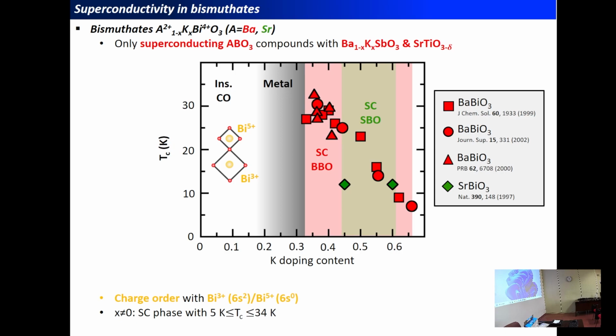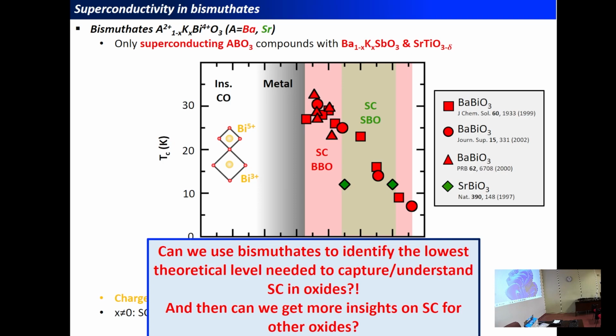But when you dope the material, either if it's barium bismutate or strontium bismutate, it's possible to reach a superconducting region in which the highest critical temperature is estimated around 34 Kelvin. And so I would like to use these systems, the bismutates, to identify what is the lowest theoretical level needed to capture and understand superconductivity in these perovskite oxides. And so can we get more insight on the superconducting mechanism if we transfer the knowledge we get in these bismutates to other oxide systems, such as the nickelates, for instance.